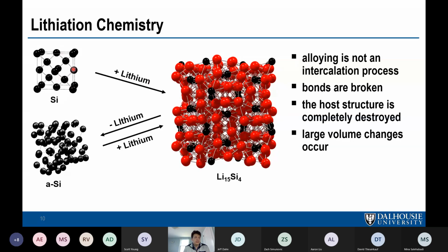Silicon has a diamond structure. There's no room really for anything else. And if you add lithium, it has to break bonds and change the structure to lithiate silicon. And what you get at full lithiation at room temperature is Li15Si4. This structure represents the closest packed arrangement of spheres of different sizes with this stoichiometry. And you can see that now you have no silicon-silicon bonds at all. In fact, you have something that looks like silicon in a sea of lithium. And this is why silicon can hold, I think it's like 16 times as much lithium per host as graphite, because you can form structures like this.